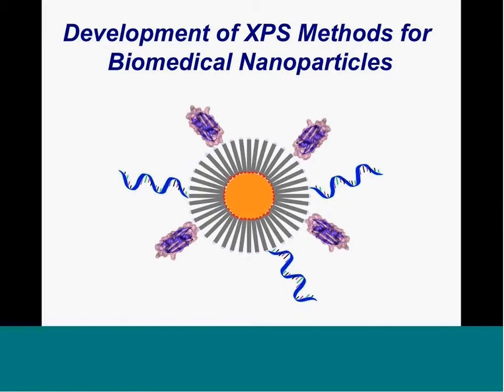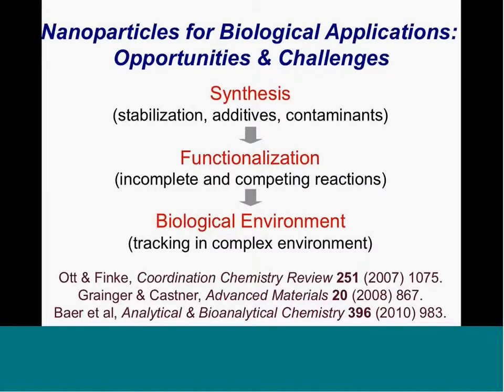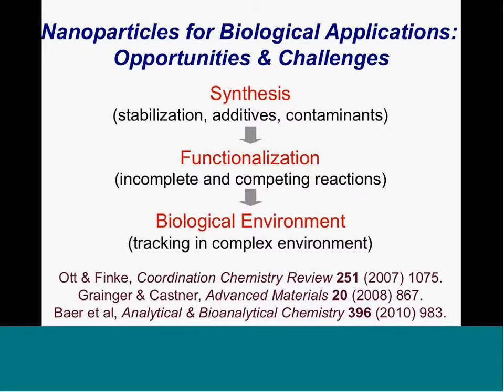I want to finish up with a few slides on nanoparticles. These have been widely used, but many people who use and fabricate them have not thought much about the surface structure or how it's functionalized. There are a lot of challenges: when synthesizing nanoparticles, there are stabilization agents, additives, and contaminants present in solution that may adsorb on the surface. Functionalization reactions typically don't go to completion and may have competing reactions. And then how do you track nanoparticles—essentially the same size as proteins—in a complex biological environment?